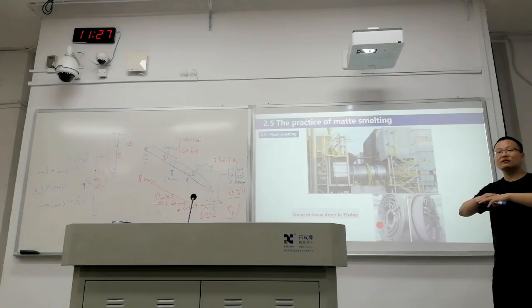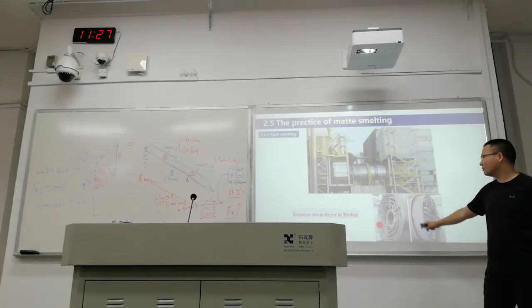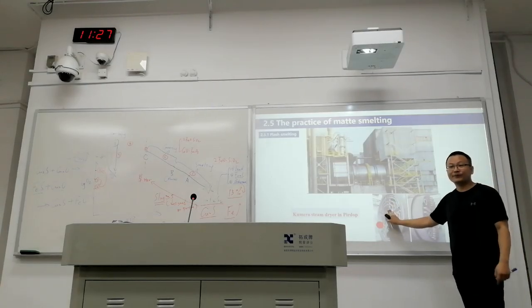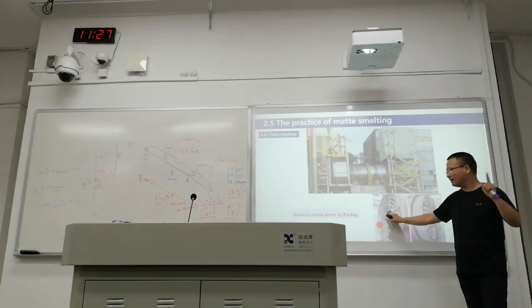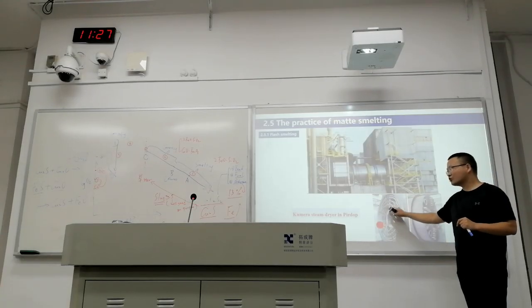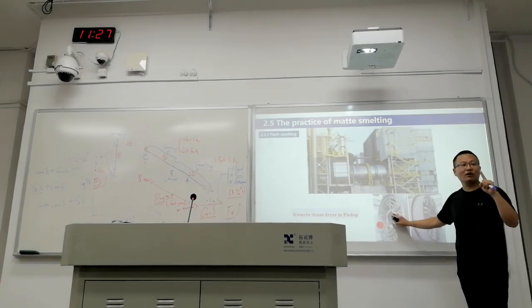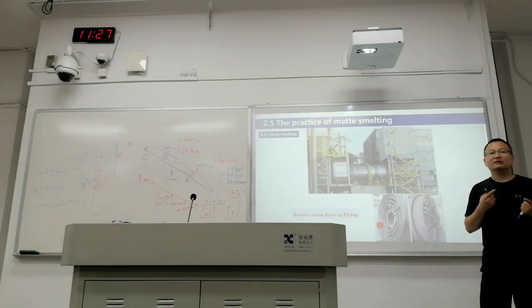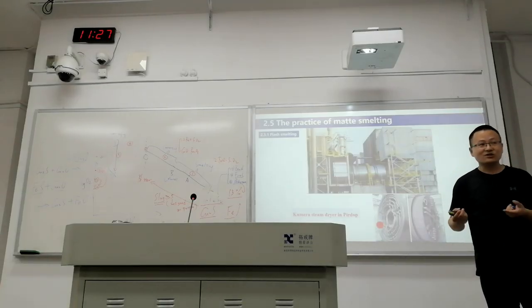There will be corrosions, physical ones. So the materials here is also critical. So temperature is very critical, and the corrosion is very critical. And what's more, there are 8 to 10% of moisture in the concentrate.